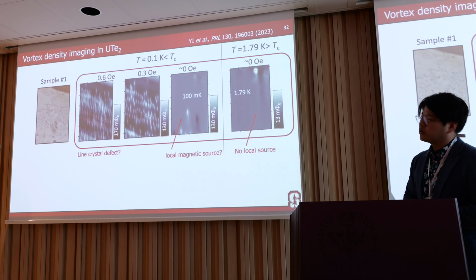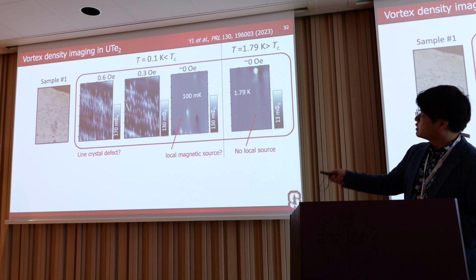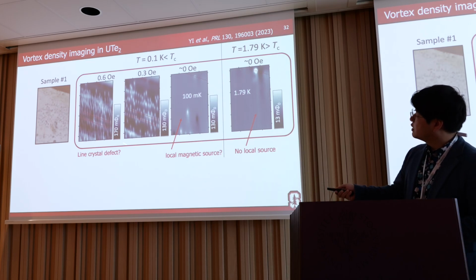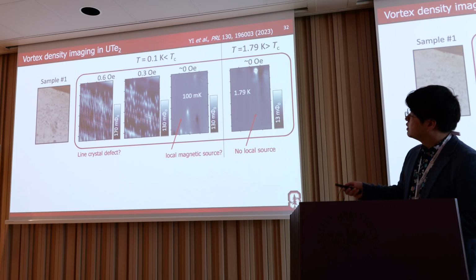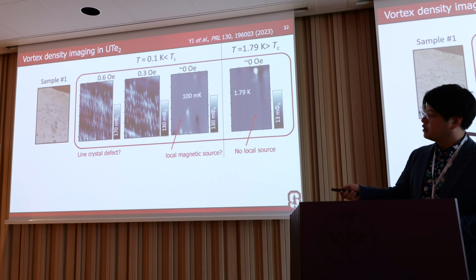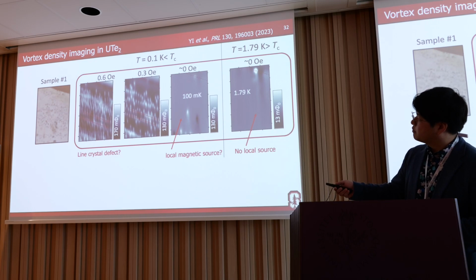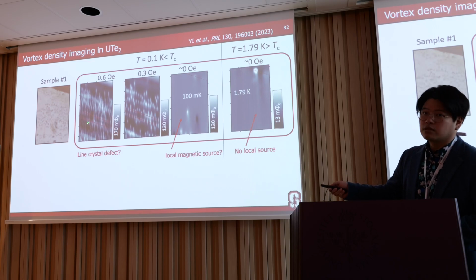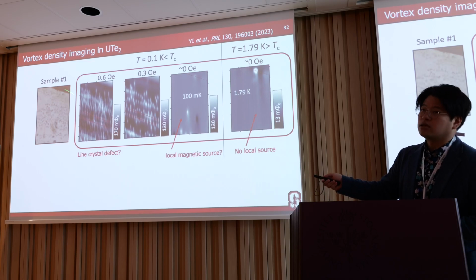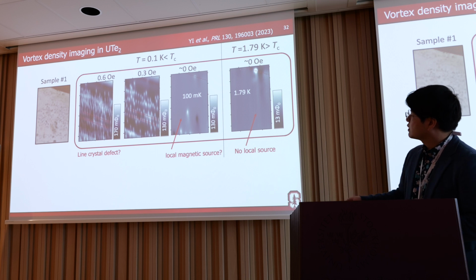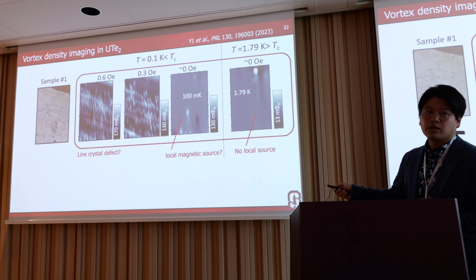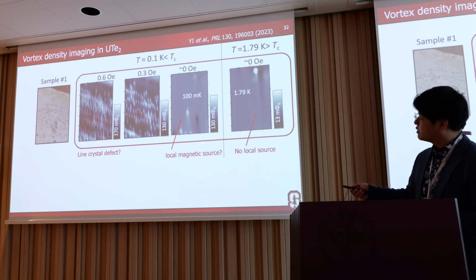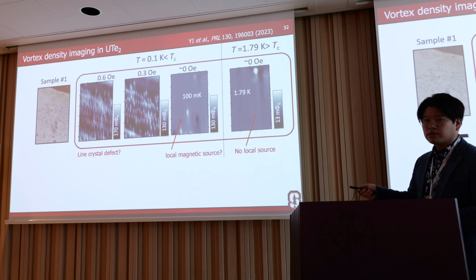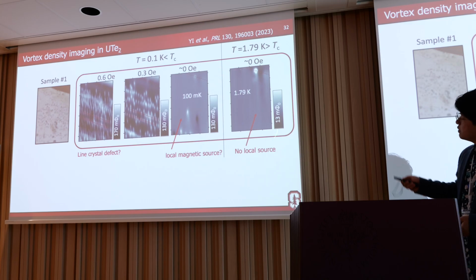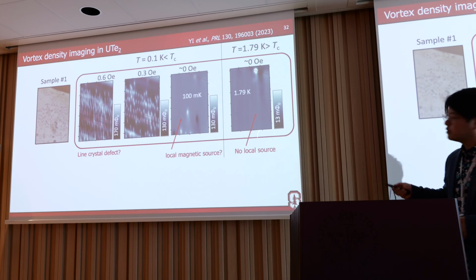We also measured the vortices, with high field cooling and zero field cooling. There are two kinds of interesting points. One is that the vortices look pinned along one direction, which is parallel to the crystal edge. The other is that zero field cooling still shows a vortex and anti-vortex. So it suggests there's a local magnetic source, but above TC there's no visible magnetic field from a local field there.